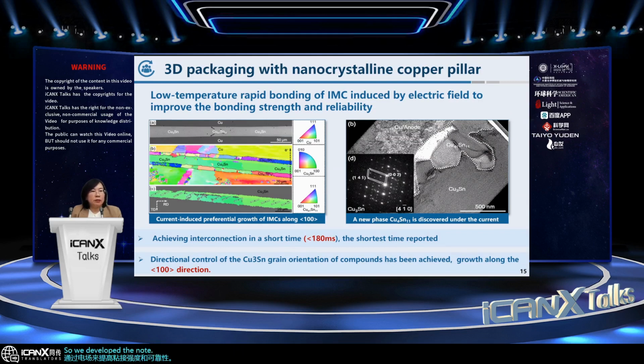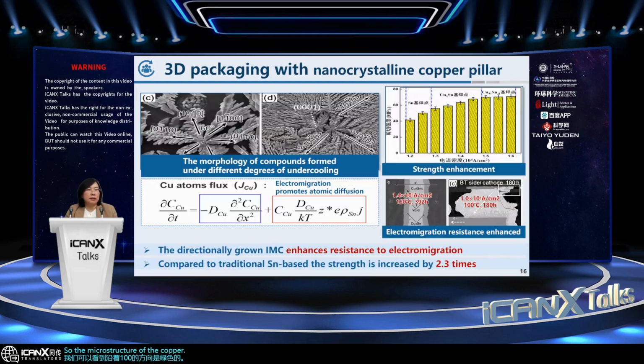So we developed a low temperature rapid bonding method and achieved the interconnection in a very short time, about 180 milliseconds. And the directional control of the intermetallic was also achieved. We can see that the grains are oriented along the 100 direction. So the microstructure of the copper pillar joint is very special, which can also enhance the joint strength. The directionally grown intermetallic can enhance the resistance to electromigration, and compared to the traditional tin-based solder joint, the strength is increased about 2.3 times.